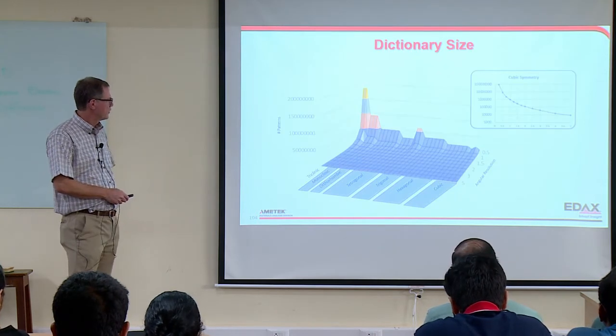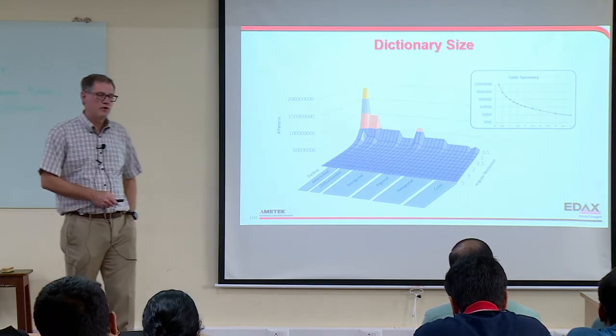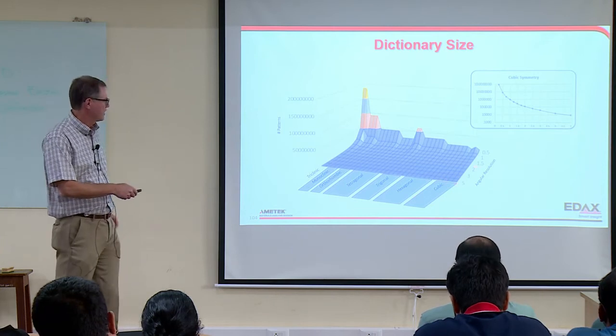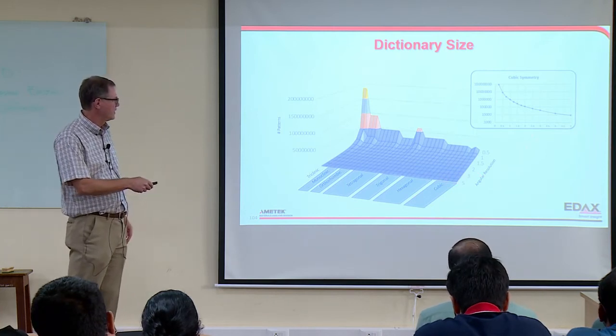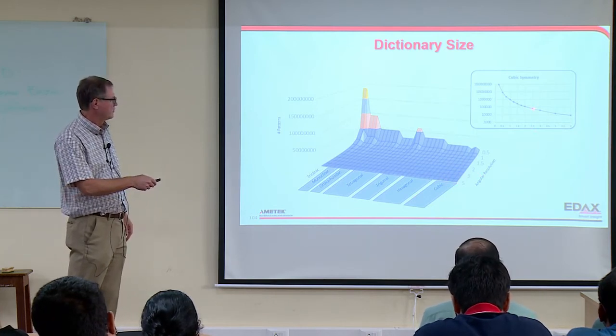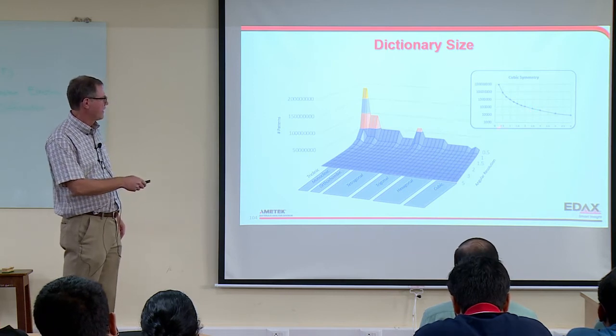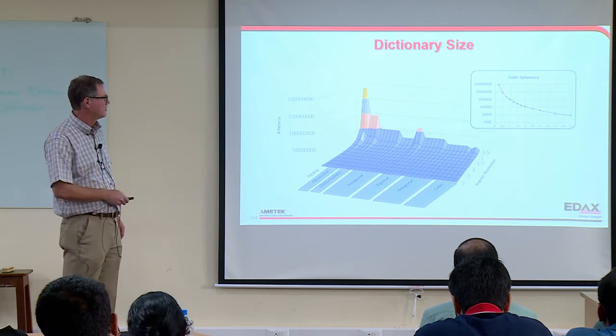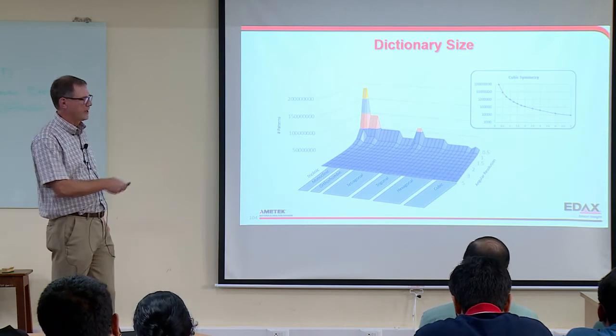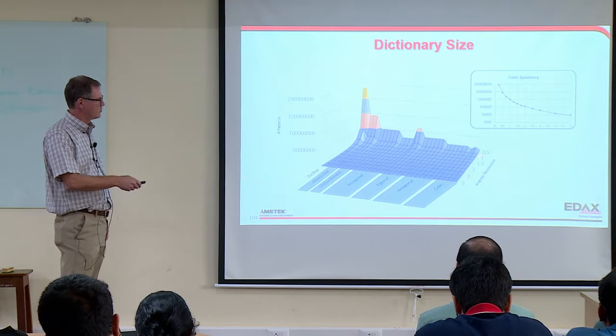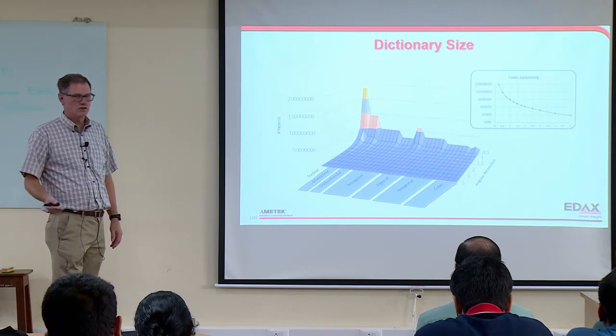Better than you could get with Euler angles. But it's a lot of orientations. So cubics, that 2.5 degree resolution was almost 100,000 points. If I were to go to 0.5 degrees, I'm up here around 1 million. If I want to go smaller than that, 10 million. So it increases really quickly with resolution.